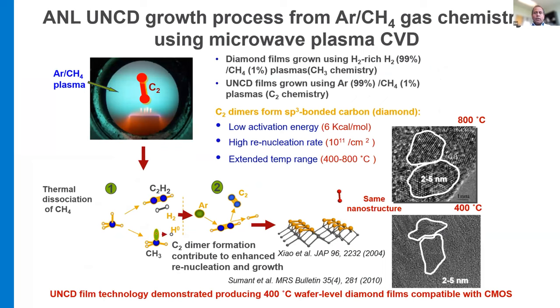Apart from that, there are various advantages working with polycrystalline diamond, and that's what I'm going to talk about today. At Argonne, we work on this ultra nanocrystalline diamond technology, which works on the principle of a different gas chemistry than the conventional hydrogen and methane gas chemistry. We use argon and methane, which mostly produce C2 as the main growth radical, which has a very low activation energy to insert into the diamond lattice.